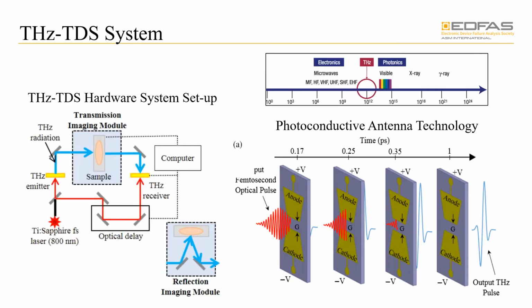So just as a recap from the previous slide, there are multiple drawbacks to multiple methods. And as we can see here, terahertz imaging is an adequate method that provides surface, subsurface, and volumetric information, which makes it a very attractive, non-destructive, and contactless characterization method. It should be noted that when we refer to these terahertz signals, they usually refer to signals that have a frequency between 0.1 to 10 terahertz, and the terahertz frequencies lie between the electronic and optical regions, which carries capability from both domains. And again, the terahertz signal is transparent to semiconductors and most of the polymer materials, which makes it even easier to use for contactless characterization.